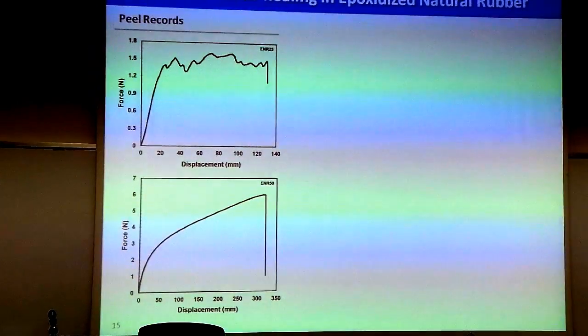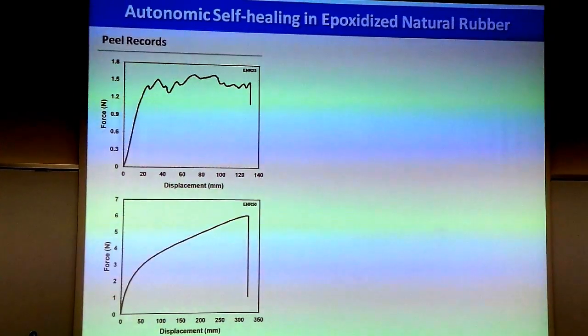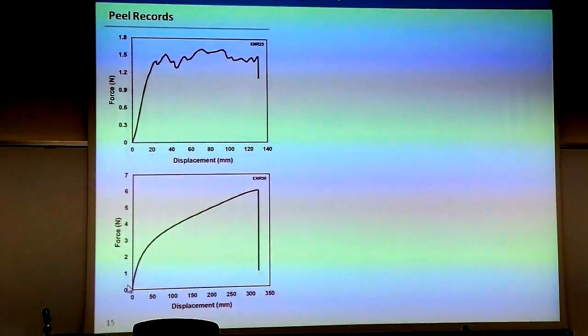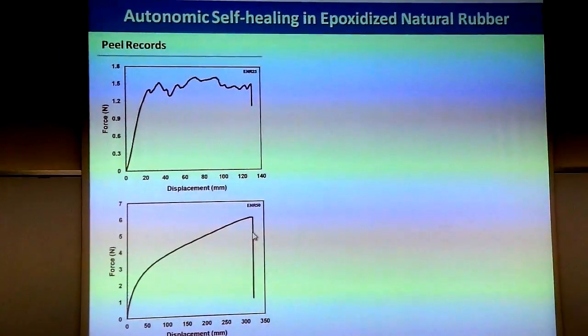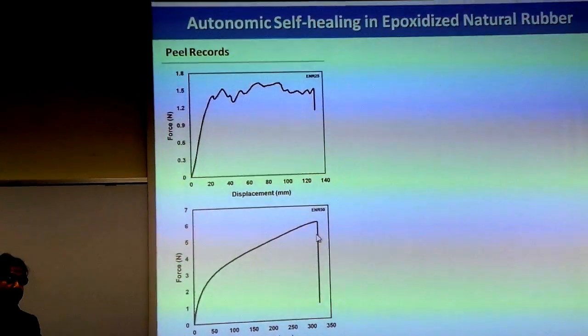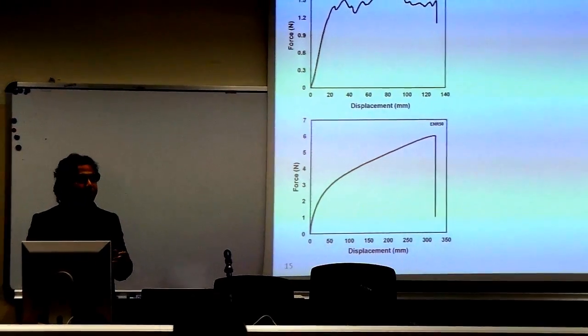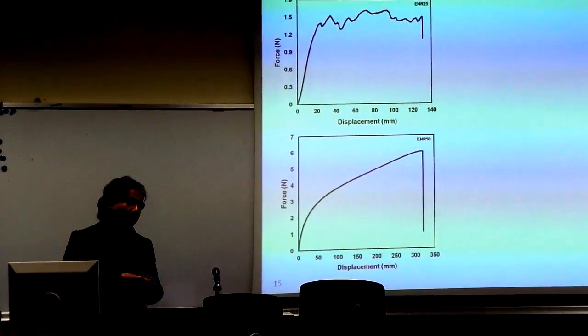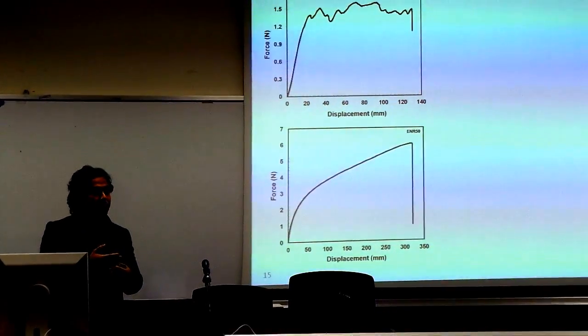This is because when we treated the sample, for example, ENR 25 sample having 25 mole % of epoxidation, I treated the sample for 30 minutes at 60 degrees Celsius. And in the peeling test, this is the typical peel record for ENR 25. But at the same condition, the ENR 50 showed a different peel record, which is more like the stress-strain curve for the ENR 50 sample. And this behavior can be ascribed to the complete cohesion at the interface of the peel sample. And this strong cohesion is supported not only by the interdiffusion of the sample, but also the interaction among polar groups can play a significant role.